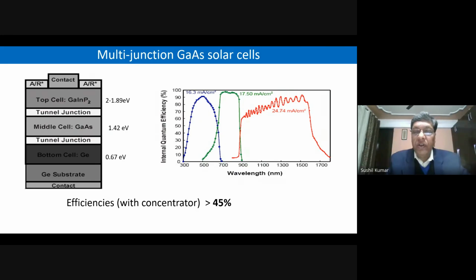And if you see, this is how it is shown here, your internal quantum efficiency with the wavelength of each cell. Like you have here three cells, the top cell, middle cell, and the bottom cell. Bottom cell with band gap of germanium, and gallium arsenide 1.42, and gallium indium phosphide around 2 electron volt. So basically, if you see the blue spectra, this is the current being produced in the top cell. Light from 300 to 700 is shown, how it is absorbed, and the current produced is 16.3 milliampere per centimeter square. In the second cell, you have this much spectral absorption. Current is also quite close to this, 17.5.